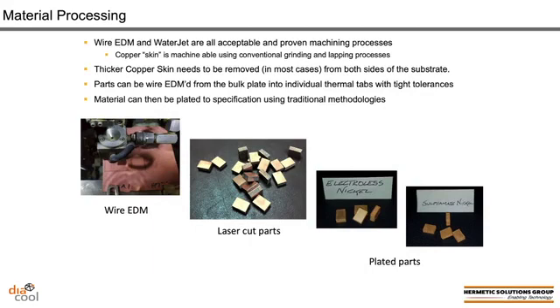So how do we prepare this material for consumption? These large area substrates of Diacool material can be wire EDM'd, they can be laser cut, as you see here in the two images on the left-hand side of this slide. The material can be cut into any shape or size. There's really no limits to the kinds of geometries that we can create with this material. It also is, because it's largely copper, it plates very much like copper and is friendly to any kind of plating chemistry that you can imagine. The images you see here of electroless nickel and gold-plated parts and sulfamate nickel and gold-plated parts are just examples of the kinds of chemistries you can use on this product. We can also add any other chemistries that you may consider.